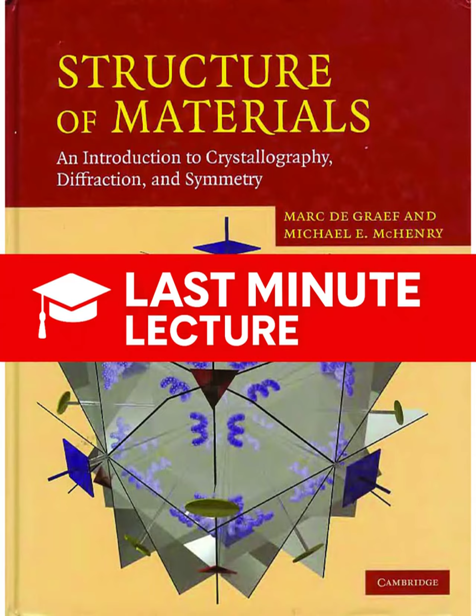Yes, the concentration of the M cations, like magnesium or iron, filling the octahedral sheet determines the classification. If the layer is fully occupied, we call it trioctahedral mica. And if not? If only 2/3 of the sites are occupied, like in muscovite, it is dioctahedral. This slight difference in occupancy changes the structural geometry and the type of stability required.